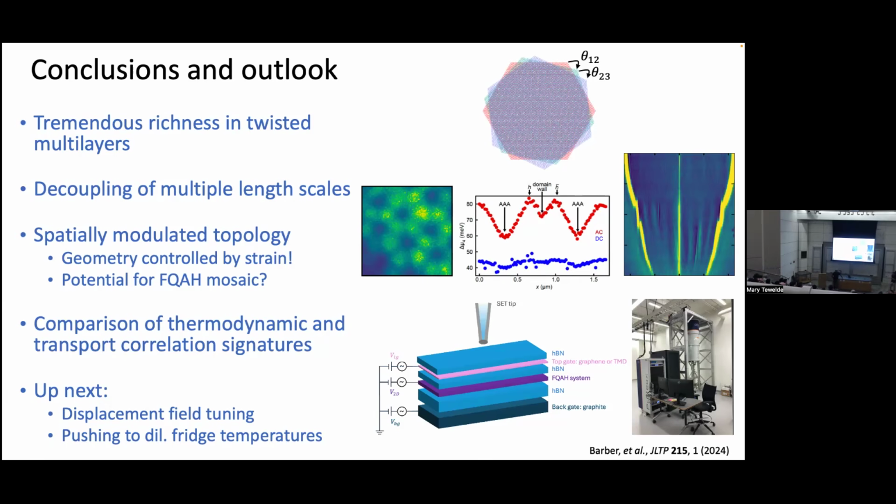Yeah, so that's a good question. I'm showing you the devices which worked. A lot of them come out imperfect and not ideal. We don't know why exactly. Certainly you want to avoid polymer residues. I think a real answer to your question is that the van der Waals adhesion is pretty good. So in many cases, as you're putting these things together, you can sometimes squeeze out dirt, or you can use an AFM tip to clean dirt or to move bubbles around. I haven't shown you AFM images because oftentimes, even for the pretty devices like this, they look disgusting. It turns out that a lot of the physics seems to survive. It doesn't always, and this is one of the Achilles heels.